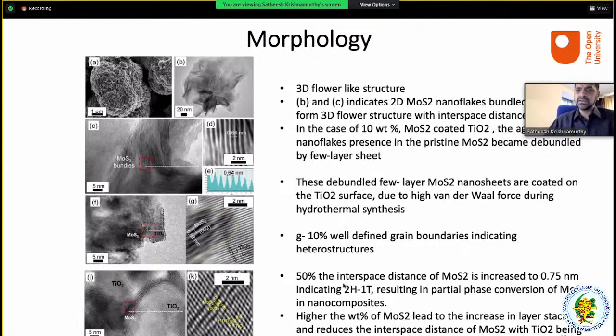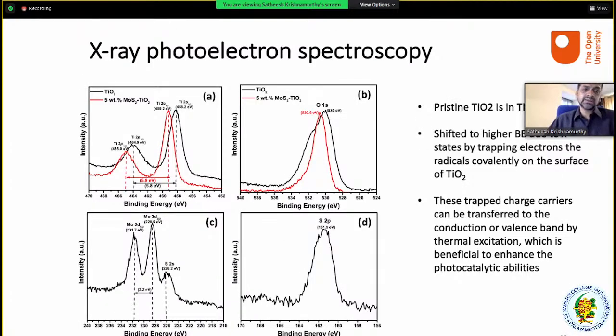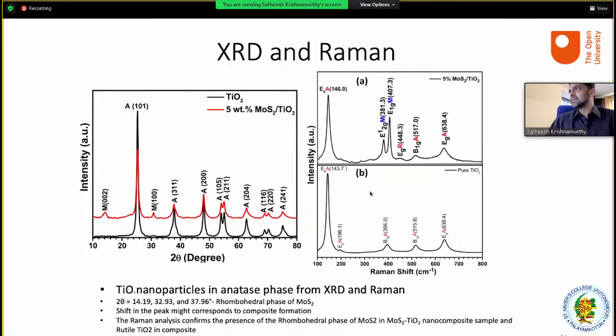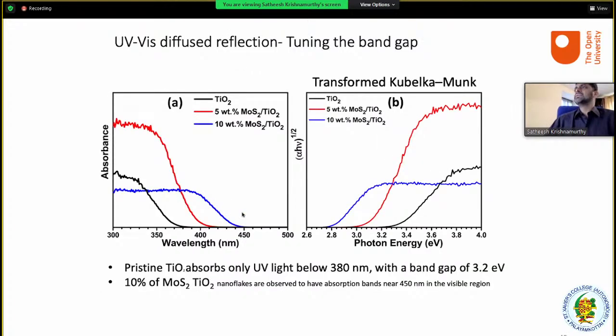These are all published data. And the XPS fingerprinting, we started characterizing this with the chemical shifts. And similarly, the XRD, with which we can start doing the band gap alignment. And then we started doing the optical absorption. This is a very important result. You can see that between the TiO2 and the molybdenum doped samples, there's a huge shift. This shift is tuning of band gap.